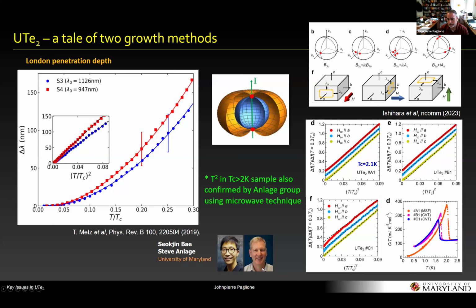And I should say that Steve Anlage's more recent measurements confirm this. So they see the same thing. It's quite a different experiment, but they see a quadratic temperature dependence in all field orientations. Okay, so I would say that there's a question about how the microwave penetration depth measurements are affected by surface states. And so I think this is an open area for both theory and experiment to investigate.